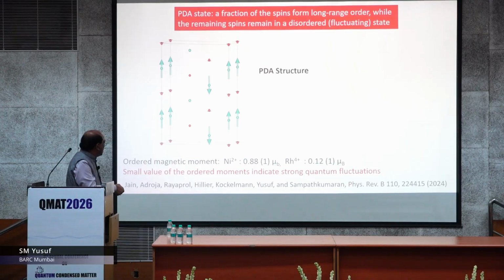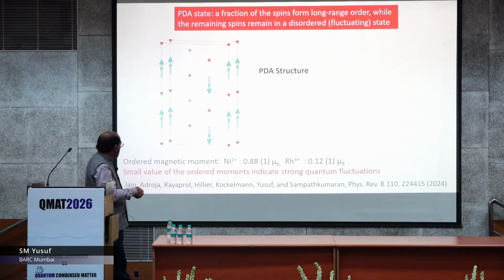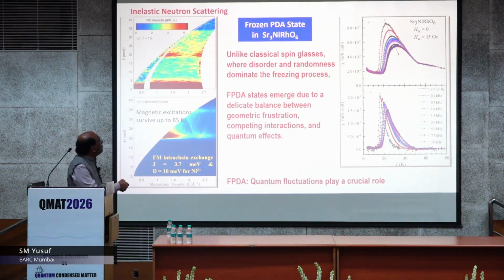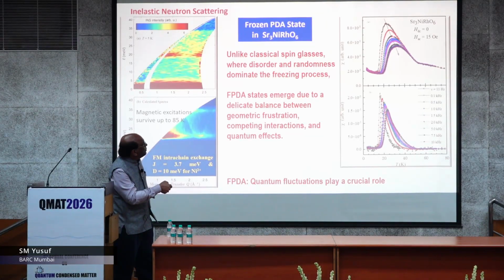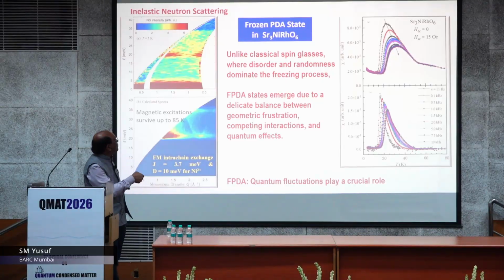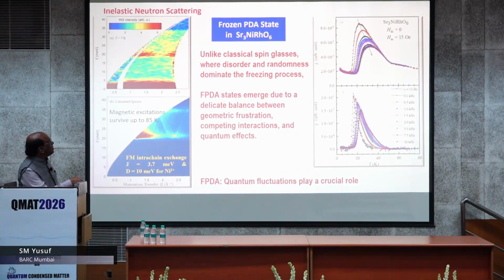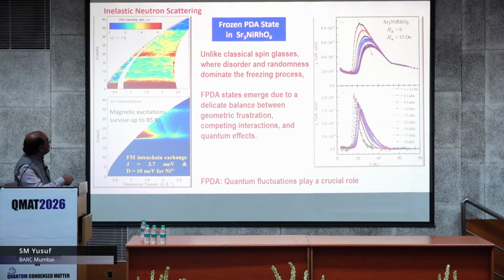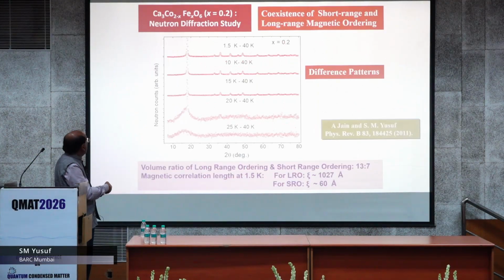This is totally disordered. And if you see this system, which we work with in collaboration with Professor Sampath Kumar and others, so their moment, nickel 2 plus supposed to have 2 Bohr magneton, rhodium 4 plus supposed to have 1 Bohr magneton, taking g equal to 1, but it is very, very less due to strong quantum fluctuations. This system, if you see the AC susceptibility with the frequency dependence, you do see this kind of behavior, and we have interpreted this as a frozen spin glass kind of thing. So the normal spin glass where you have both disorder and randomness, that causes freezing, but here the quantum effect is coming in, and from the inelastic neutron scattering study, what we see here is that these excitations we see much beyond the so-called ordinary frozen spin glass temperature, which is around 20 K, here right up to 85 Kelvin. So this kind of new novel properties we see.